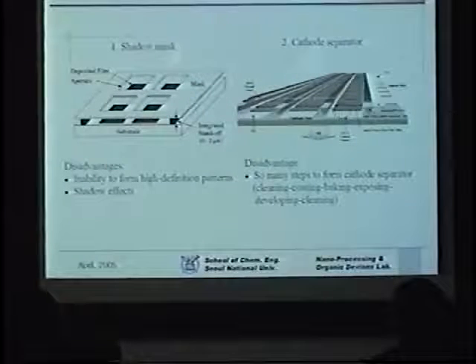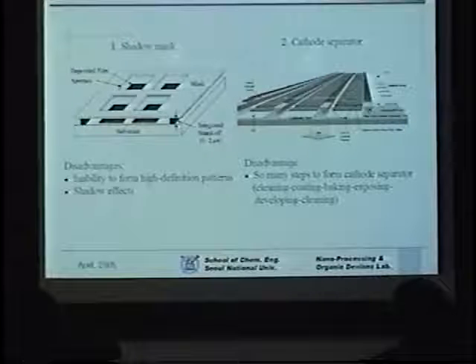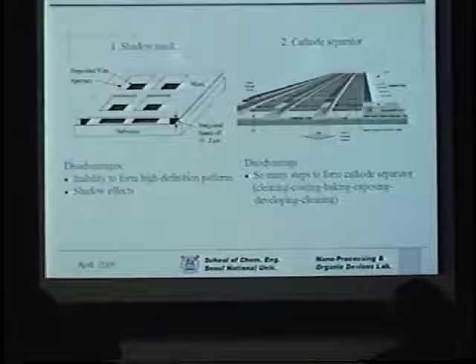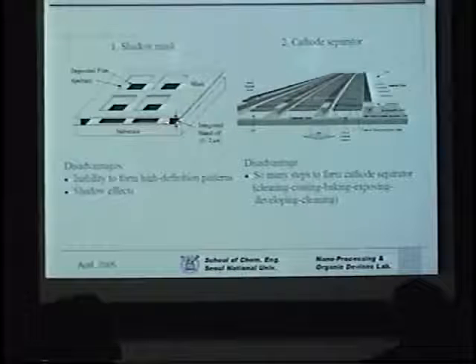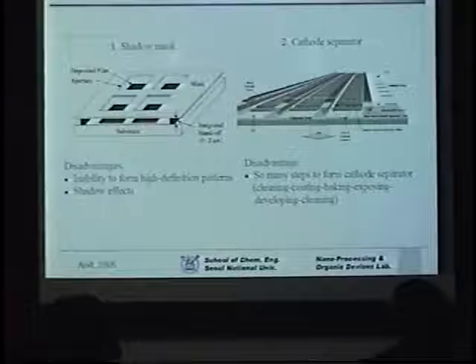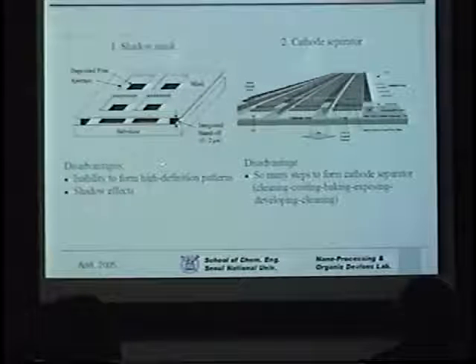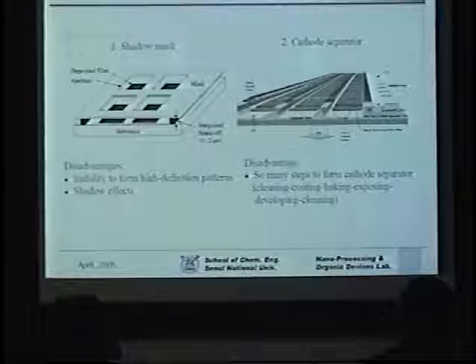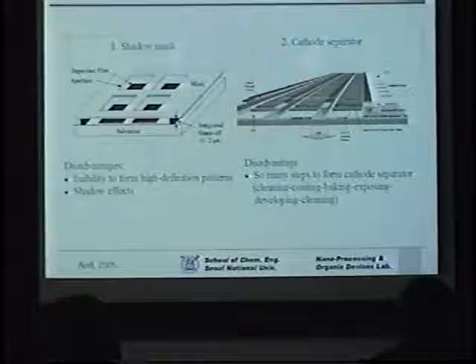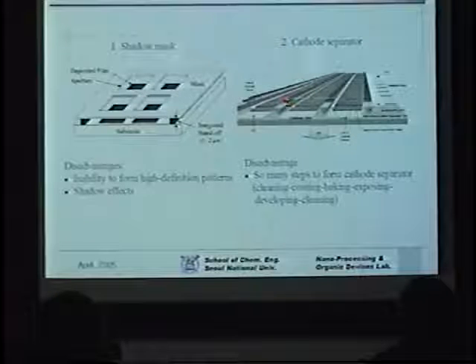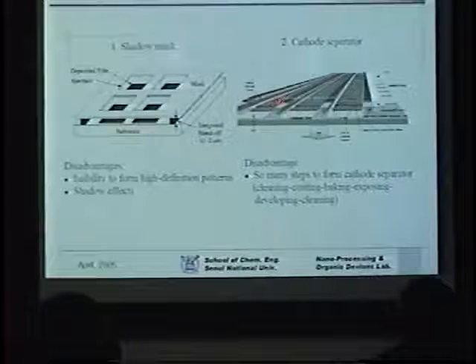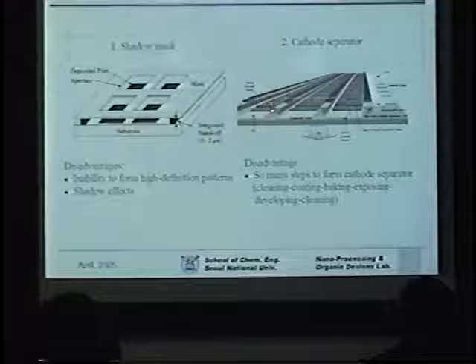So in this patterning, the conventional, I should say the traditional, approach is typically to use a shadow mask. In this case, you have a shadow mask separated from the substrate by a certain distance, and through the opening you deposit the material of interest to you. And of course, because of this gap, you can have shadow effects, and it's very difficult to go down below, say, 30 micron. Another approach is to use what is called a cathode separator, and you make the cathode separator, shown here, through photolithographic means, and then you deposit the material in succession, for instance in OLED, to make the devices.